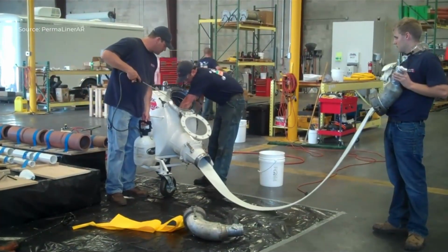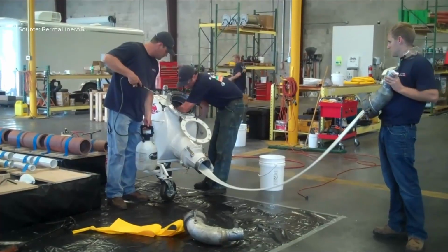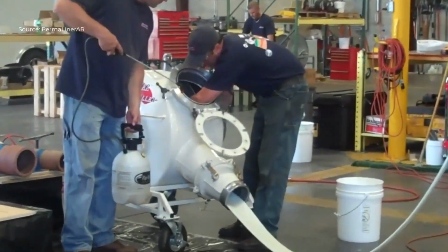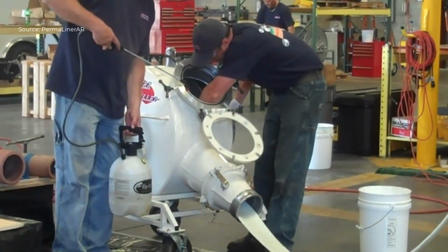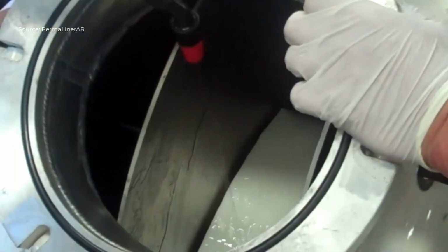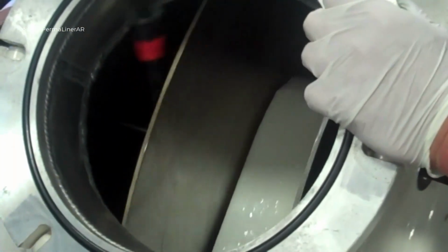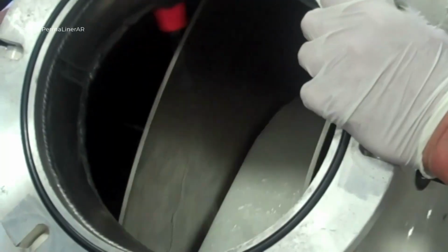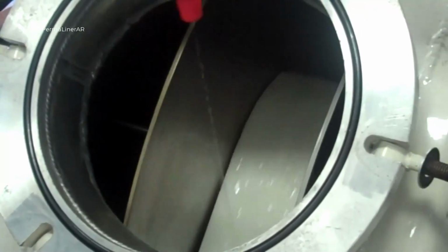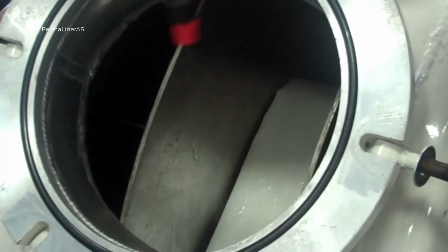Then, the liner is placed into the inversion head, which is attached to the pipe opening. By applying compressed air, the liner is turned inside out as it advances through the pipe. As a result, the resin-coated surface of the liner comes into direct contact with the inner walls of the host pipe, ensuring a tight bond and smooth fit.